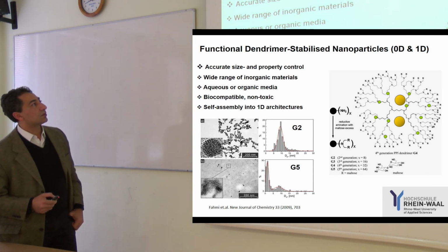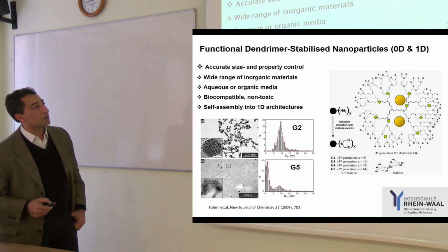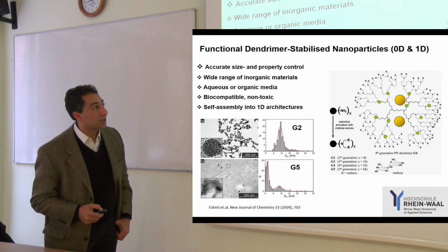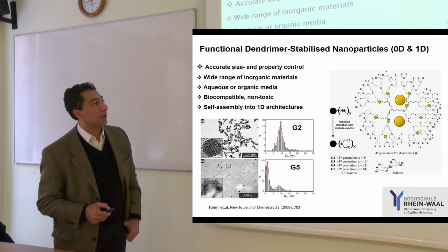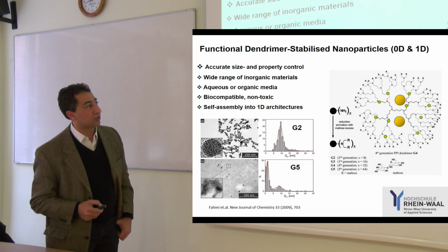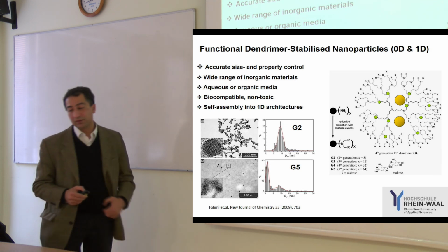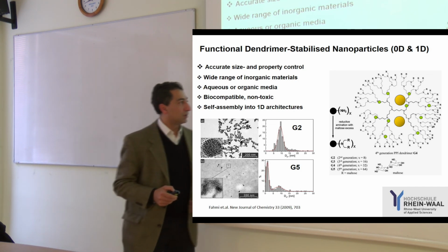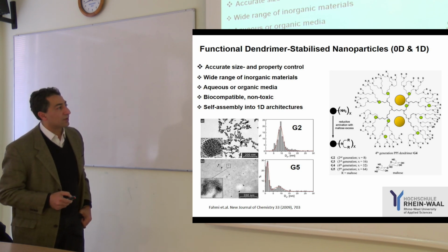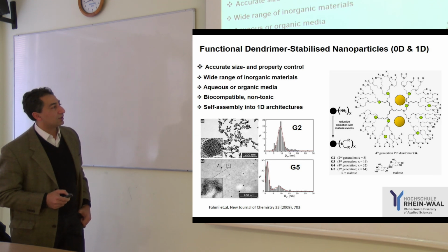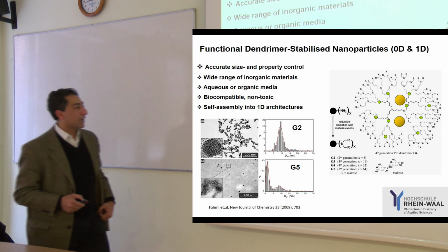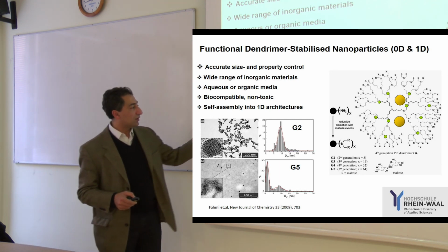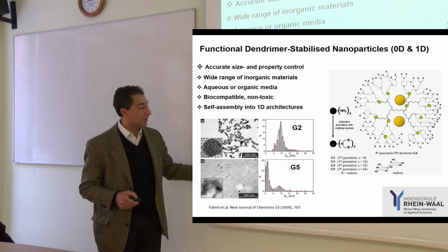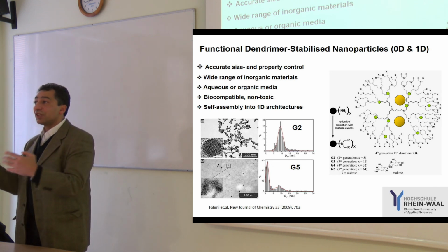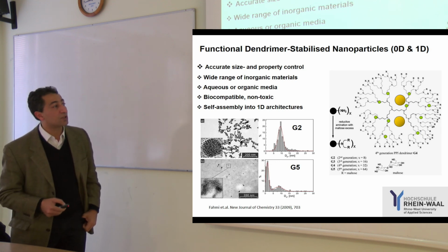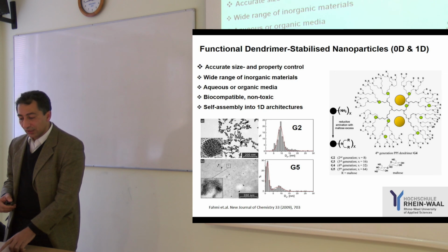Interestingly, all of this can be done in different media. As you see here, we can use dendrimers as reactors, where we can control different levels of growth mechanism inside the cavity of the dendrimers, or we can adjust the charge around the dendrimers to get different levels of structure. If you use a very small generation, for example generation 2, you can have a very nicely aligned inorganic nanoparticle, in this case a gold nanoparticle, or we can use higher generations to get a bigger nanoparticle size. As I mentioned before, according to the generation, we can have different mechanisms of growing the inorganic within the dendritic matrix.